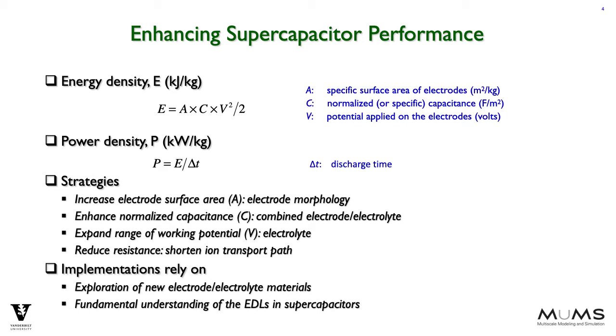Based on these equations, the strategies for improving supercapacitor energy density are to increase the electrode surface area. This is why we use nanoporous electrodes. To enhance the capacitance, which is a function of both electrode and electrolyte. To increase the voltage V, which is primarily a function of the electrolyte, since it means using an electrolyte with higher electrochemical stability. To improve power density, we need to enhance transport properties and reduce transport times. Often the question reduces to, how can we improve energy density without compromising power density? To do this means exploring new electrolytes and electrodes, and to reach fundamental understanding of the electrical double layers in supercapacitors, which is the goal of FIRST Center research.